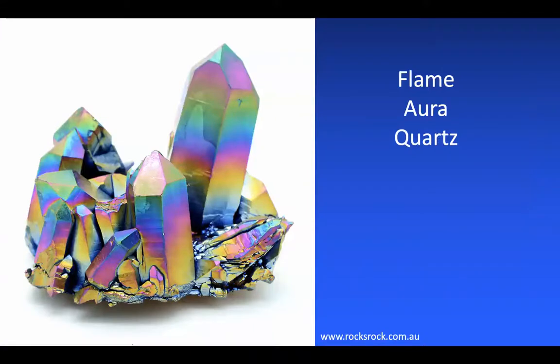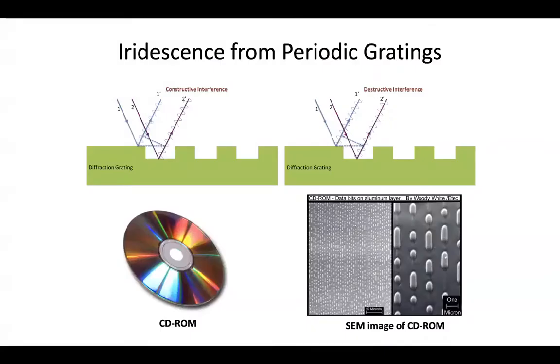And gem dealers have taken advantage of this behavior by spraying crystals of quartz with very thin films of titanium metal in order to generate this kind of thin film iridescence. And so this takes a lackluster group of clear quartz crystals that might sell for just $10 or so. And by applying this thin film of titanium, you can achieve this iridescent effect that they call flame aura quartz, and it costs a lot more money. In fact, my mother-in-law really loved the flame aura quartz pendant that we bought her. She wore it all the time.